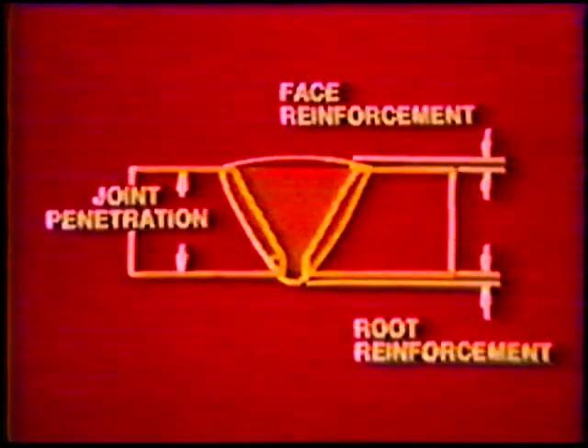One of the most common defects deals with penetration. Joint penetration is the amount that a weld extends from its face into the joint; this does not include face or root reinforcement. In some cases, penetration may be insufficient — that is, the penetration is less than required. This problem may occur because the welding current is too low, the travel speed is too fast, or the electrode is contaminated.